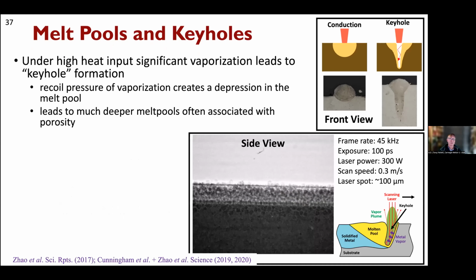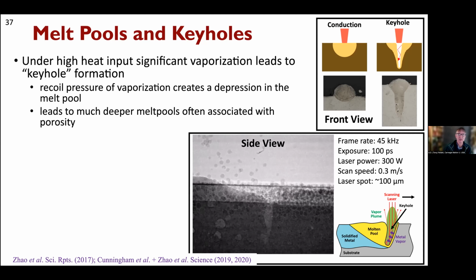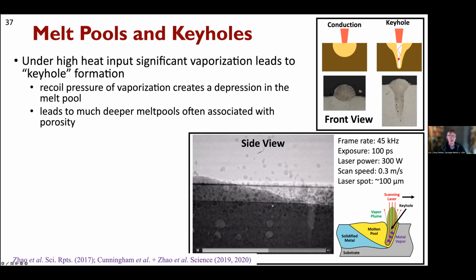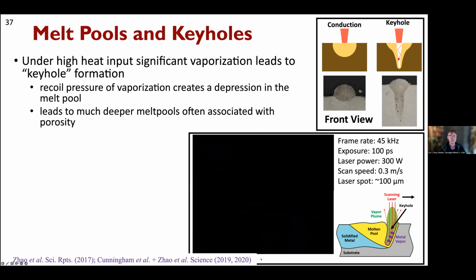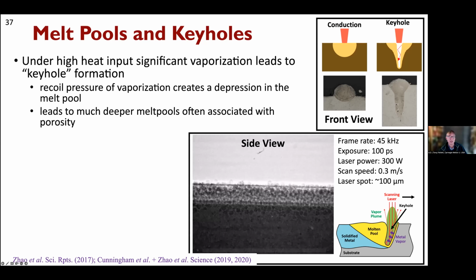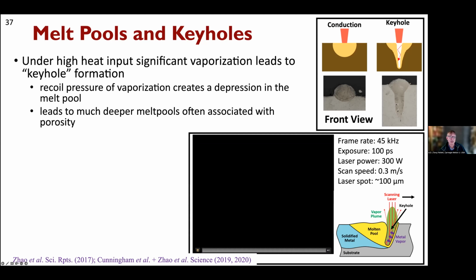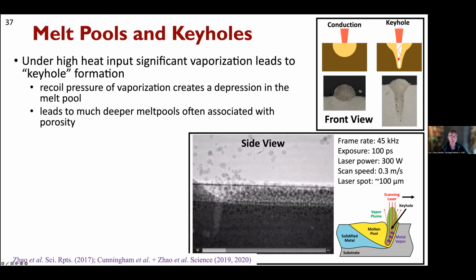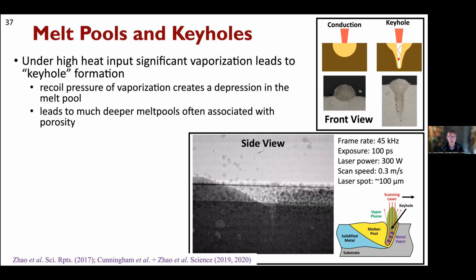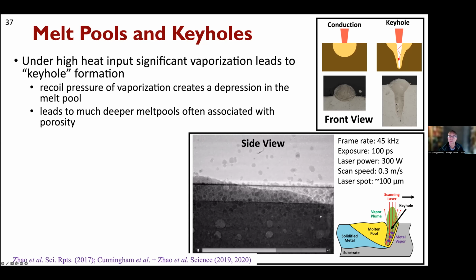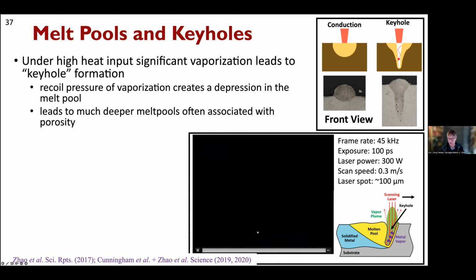All right, so let's turn our attention to the actual melting process. Again, I'm sorry if you've seen these videos many times before, but maybe not everybody has. What you're looking at is a movie where we've done this at 32 ID, and we are sending pink beam actually through a sample. It's a couple of millimeters wide. And what you're looking at is not the melt pool. You're seeing the vapor hole. The intensity of the laser light is sufficient to not just melt the metal, but actually boil it.